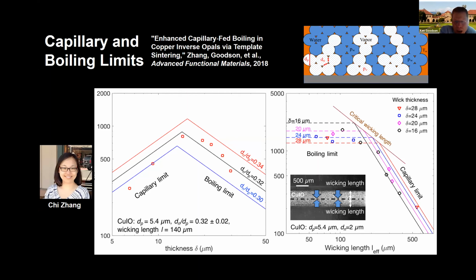Now, many of you may know, but you may not know, pretty much every laptop and a growing fraction of portable devices have heat pipes in them. A heat pipe is essentially a long structure that has a porous medium integrated inside, and the porous medium wicks the liquid that's inside to the hot region. In the laptop's case, it would be the microprocessor, and then it evaporates, and then it recondenses in the cold portion, and that would be typically near the fan in the device and near some holes where the air is blowing out. And so these heat pipes are limited by the distance and how long you make them, and that's something called the capillary limit.